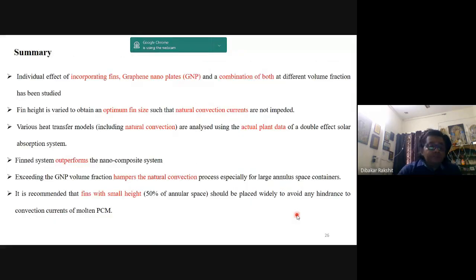So these are some of the highlights. There was a 3% reduction in the melting time observed when we are increasing the fin height from half to 3/4 of the R minus r of that annulus, capital R minus small r. And the temperature of course drops exponentially with the fin length, which we always know. And this increase in fin height actually requires more material, which is making it quite bulkier without having any effect on the heat transfer required for dissipating the heat from the system. And the melting time, if we are having a combination of this optimized fin and graphene nanoplates, is actually getting reduced by 68%. So this was one of the observations.